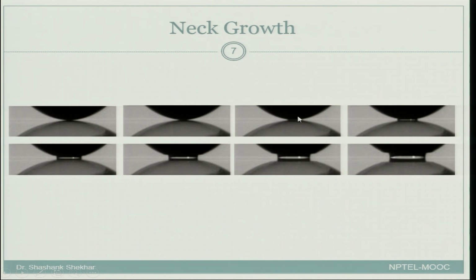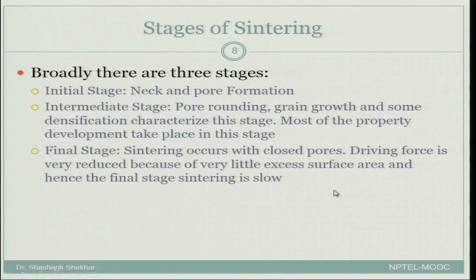So, a large amount of surface area has been reduced, and slowly you see initially if you were to compare it with sintering, there is a very large sintering rate over here, and the neck is growing, x is growing even further by addition of small amount of particles at the neck region. And once this neck becomes large enough and the radius of curvature reduces, then the sintering rate reduces. So, that is how in general a neck growth takes place.